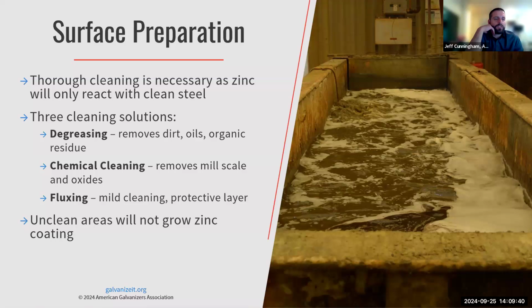So a little bit more about surface preparation. It's just absolutely necessary as zinc will only react with clean steel. Kind of went over these already, jumping ahead of myself a little. Degreaser for dirt and oils, chemical cleaning for mill scale, oxide, and rust, fluxing for mild cleaning, and then that protective layer so it doesn't pick up anything. Because once again, unclean areas will not grow that zinc coating and you'll have bare spots.